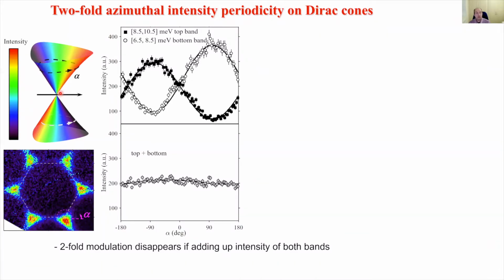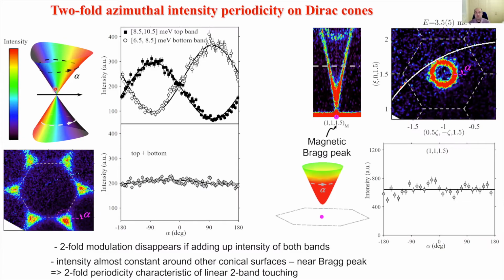Now, this is a non-trivial effect. If we add up the intensity in the two bands, we get something that's smooth, essentially constant. And to see that this intensity distribution is non-trivial, let's look at another conical dispersion surface, this time above the Bragg peak. Okay? So this is the Bragg peak. We know we have a small gap, and there's a conical dispersion above it.